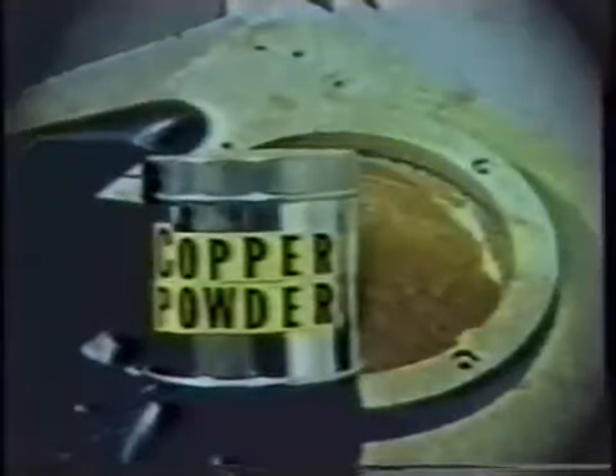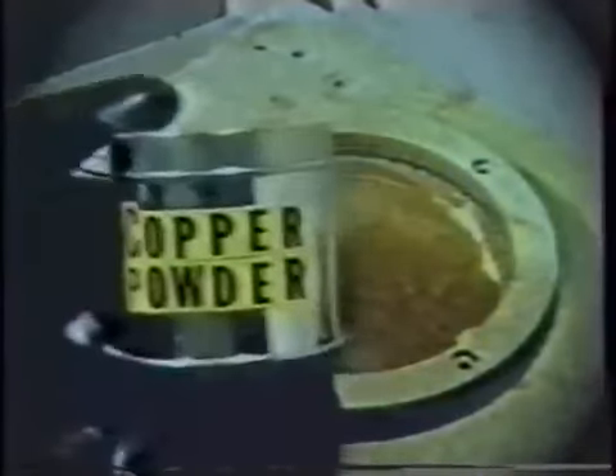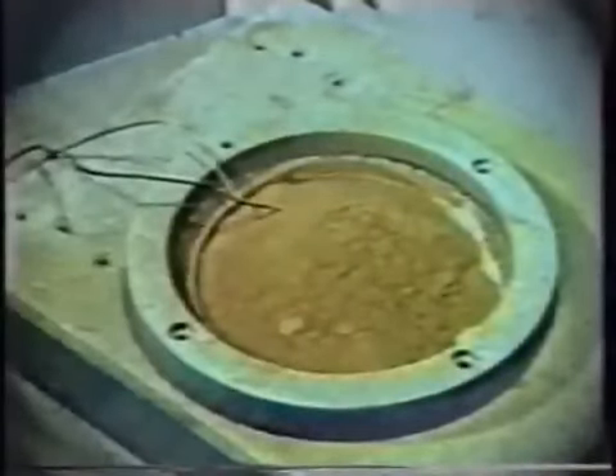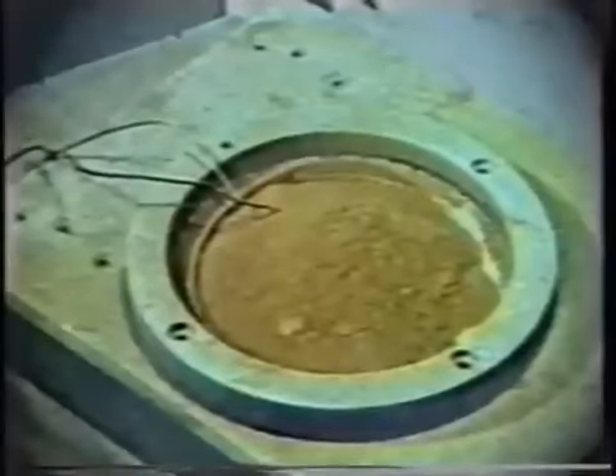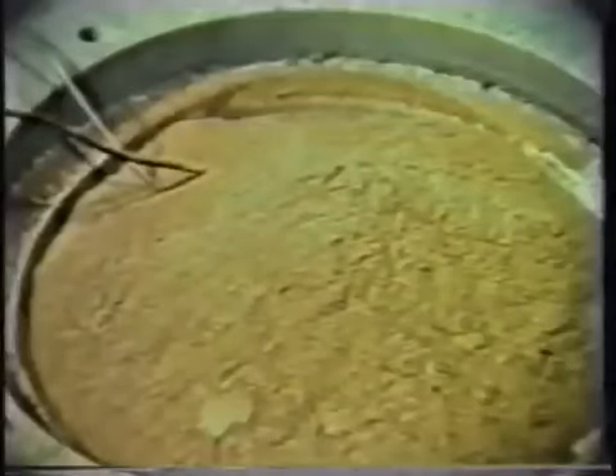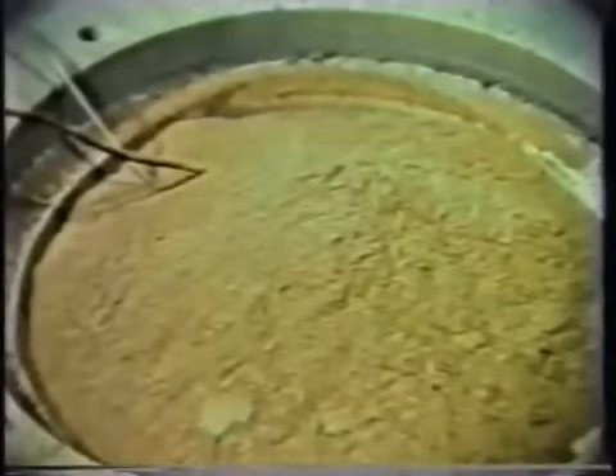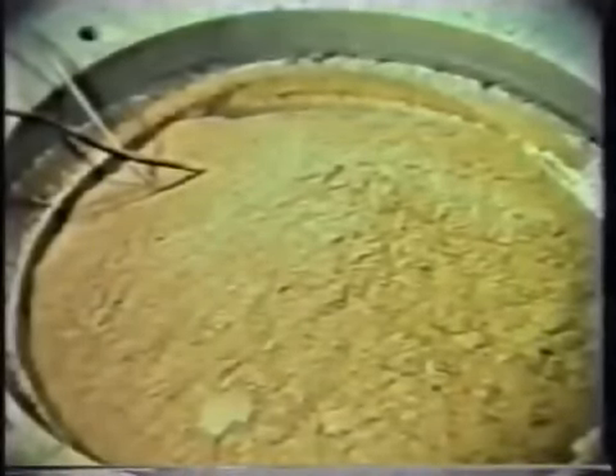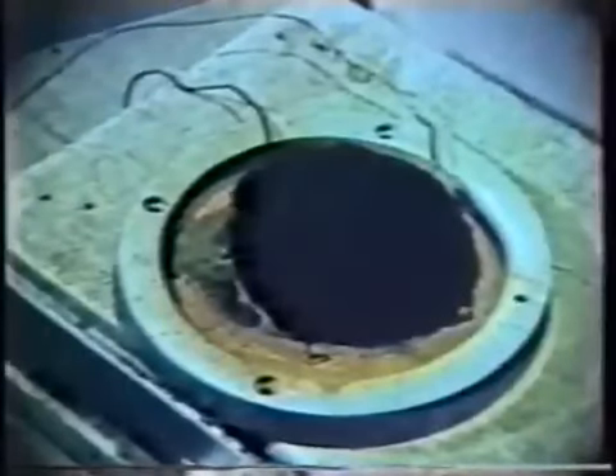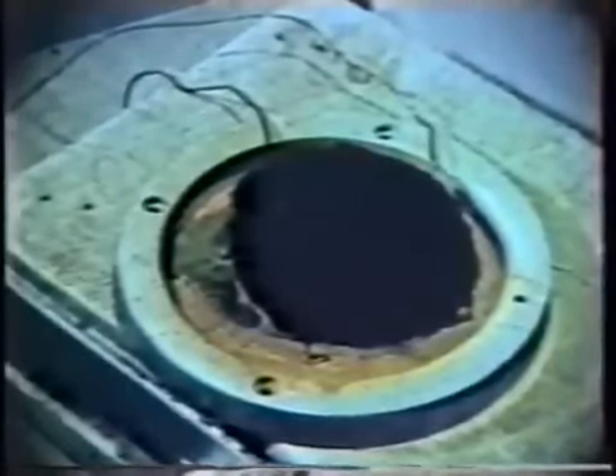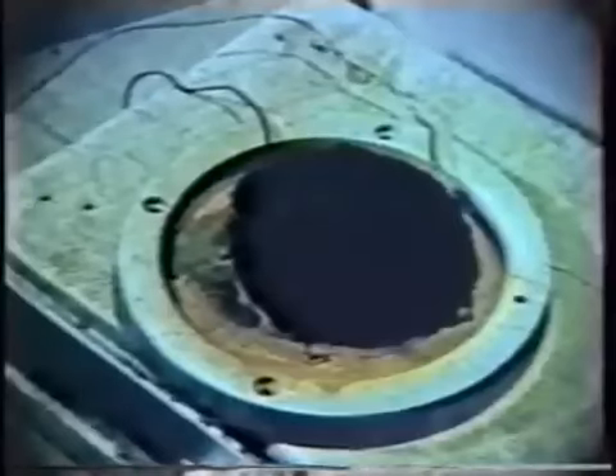There were other things such as copper powder, which might be even a better smothering agent as well as a heat removal agent. Again, this was tried, and unfortunately it did not work either. Again, there was just not enough heat removed. The fire continued to burn, and after a while all we had was oxidized copper metal powder, but the fire is still continuing to burn underneath.